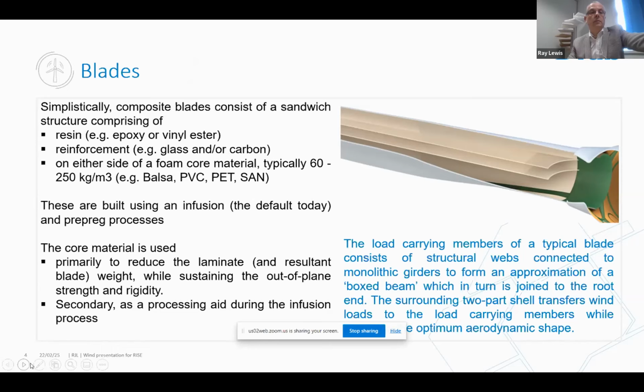So, typically in an infusion process, you use some form of medium, a mesh, to transfer the resin. And one way you can do that really cost effectively and more sustainably is to actually put appropriate grooves into the core material and get that to be used as a processing aid. In the case of the prepreg application, of course, that doesn't apply, but it's an additional benefit.